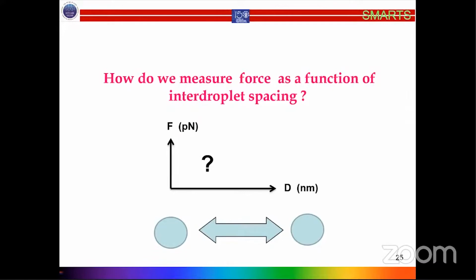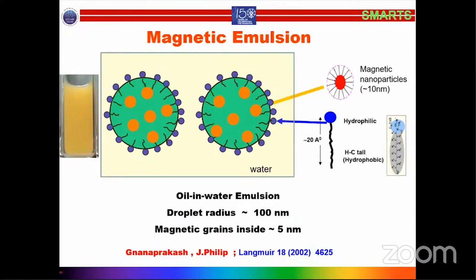So here the liquid or the magnetic emulsion which I have shown, showing different colors, is very, very useful to probe such interaction. All you need to do, if you're working with an emulsion, is incorporate some nanograins inside, so it becomes magnetically polarizable. In this particular case, the diameter is 200 nanometers and the grain size is around 10 nanometers. You put a lot of grains inside and make this magnetically polarizable.